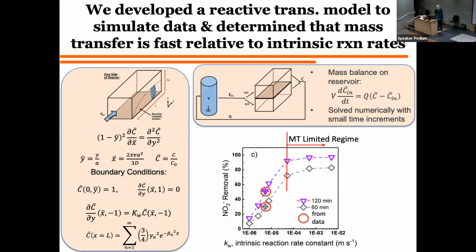So from that, we decided to try nitrate. We have a really good potential, -0.6 volts. We get high activity. We get good selectivity for N2. It's stable. It's not decaying over time, that activity. We also are not limited by mass transfer. So let's try nitrate now.